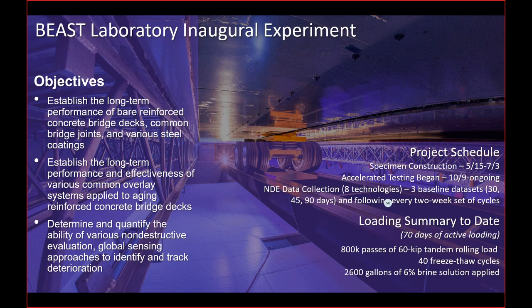800,000 passes of 60 kip tandem rolling load have been done. So the capacity of this rolling setup is about 60 kip. We have done 40 freeze-thaw cycles, and we have put on the deck about 2,600 gallons of 6% brine solution. So with that, I will pass it on to Dr. Braley to take it further and give you some more details.